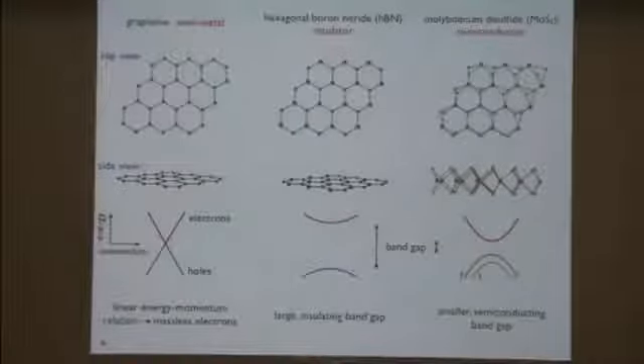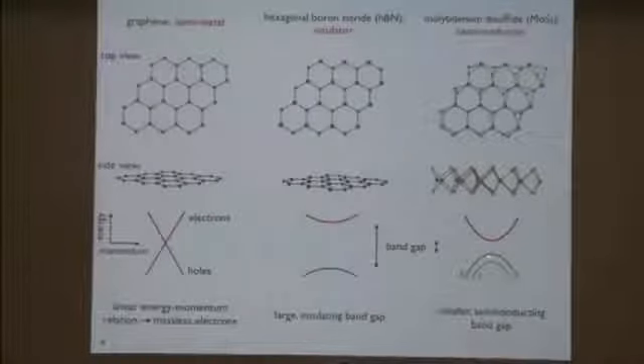And it's kind of the first thing you want to know about some semiconductor or insulator to characterize its properties. And then the newest addition to the toolbox of these atomically thin materials is this class of materials represented by molybdenum disulfide, and its structure is a little bit different. It's actually composed of stacks of atomic trilayers. So there's a layer of molybdenum atoms in the center that's sandwiched between two layers of sulfur atoms. And its band gap is intermediate between boron nitride and graphene. It's a semiconductor. And in addition, unlike graphene, it has another property, which is a strong spin-orbit coupling, which just means that the energies of the holes in this valence band depend on the direction of the spins of those holes.